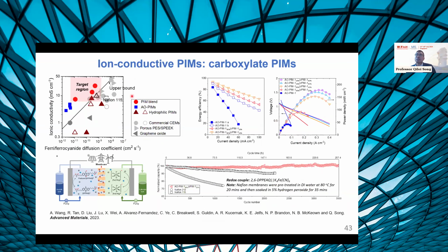And you can see that, this is the result. As expected, by enhancing the ion conductivity, we were able to improve the energy efficiency. You can see that compared to the original AOPIM1, these blend membranes give much higher energy efficiency in the flow batteries, and they can also retain the selectivity. And we were able to demonstrate that the battery was still able to operate with very high cycling stability.